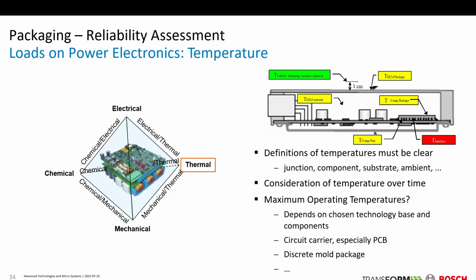The next point, quite important, is that the absolute temperature value is not so important. Okay, it is for sure, but please consider temperature over time. Really important is temperature over time, because a lot of materials can withstand really high temperatures for a short time. A lot of polymers can withstand even 250 degrees C for a few seconds without any stronger aging or degradation. But it's a question of loading of 5 or 10 seconds. If you want to discuss all reliability aspects, you have to discuss temperature over time.